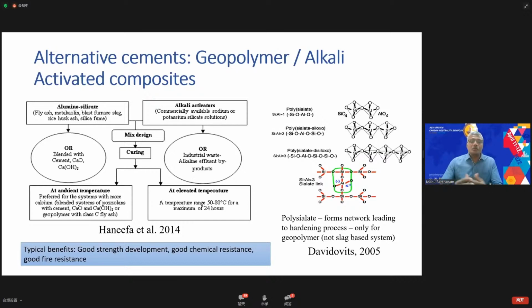The only problem is handling alkaline solutions like sodium or potassium silicate and sodium or potassium hydroxide to activate the aluminosilicates, which can be quite hazardous in a regular construction environment, so it has to be done very carefully. Essentially, it dissolves the aluminosilicate and recrystallizes it in a form that leads to hardening and strength development, so alkali-activated composites could be a potential solution for reducing the impact of cement in concrete.